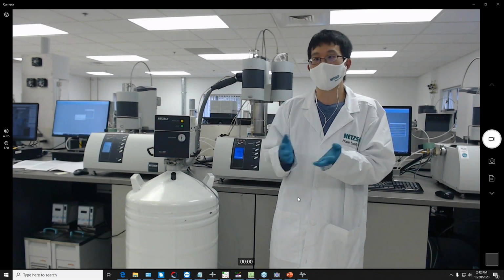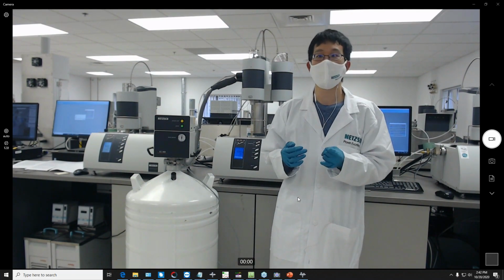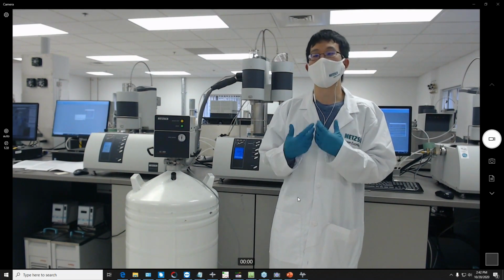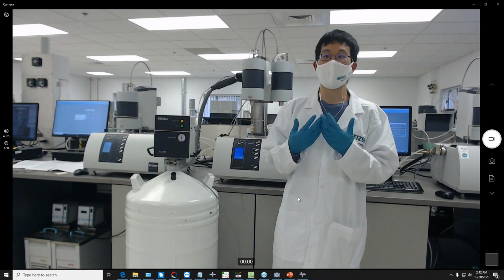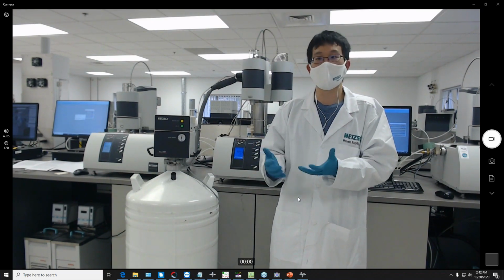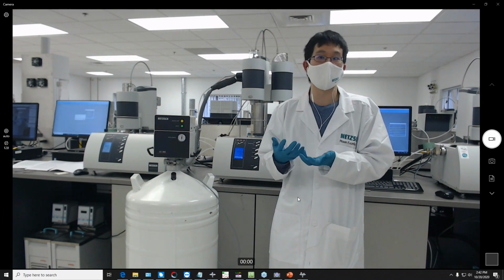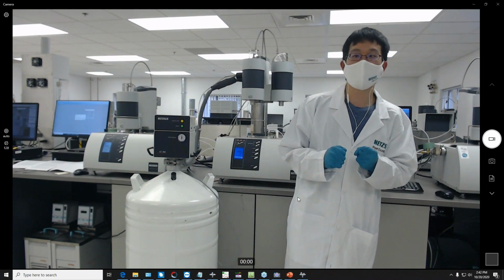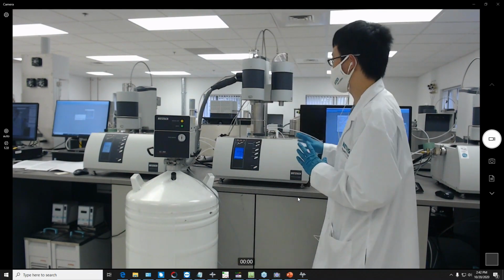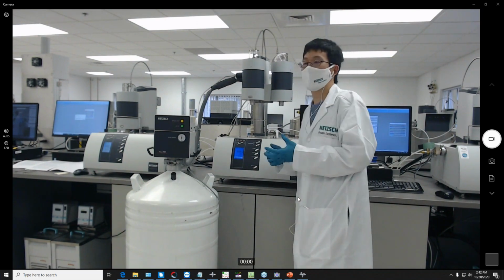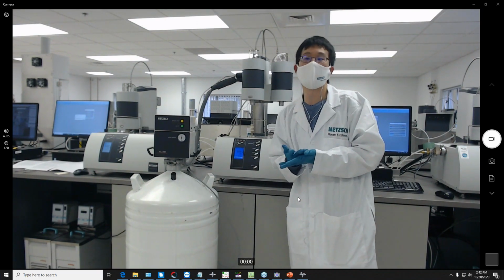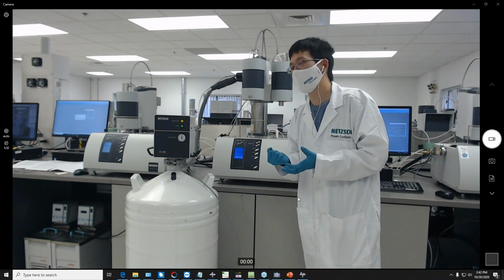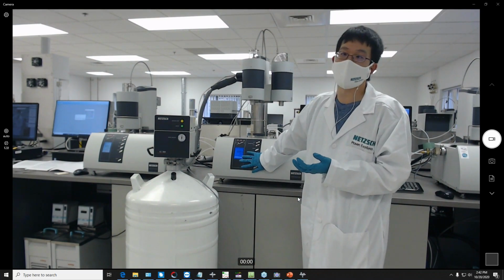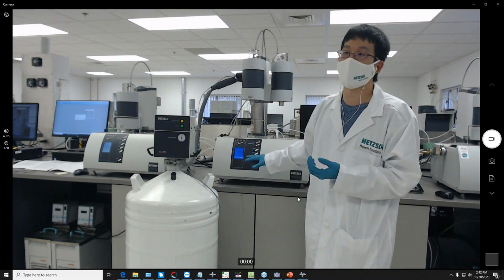Usually what I recommend is starting with small quantities of sample, test it, and then assess after each run. And if you deem that everything looks good, then you can increase the sample quantity. In terms of gas flow rates, for the STA unit, we usually recommend a minimum of 70 milliliters per minute total flow rate, in which 20 milliliters is in the protective, so that will go to the balance.